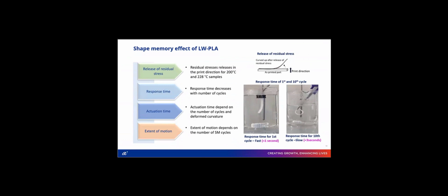Overall, from the shape memory effect, we understand that the residual stress is affected by the infill pattern and the extrusion temperature, and the release of residual stress is always curved up towards the print direction of the part. The response time decreases with the number of cycles. The response time for the first cycle is fast, less than 1 second, and for the 10th cycle it is slow, nearly 3 seconds. So the response time, the actuation time, and the extent of motion depend upon the number of cycles as well as the deformed curvature of the sample.